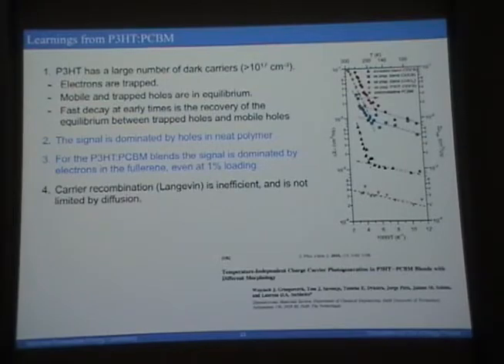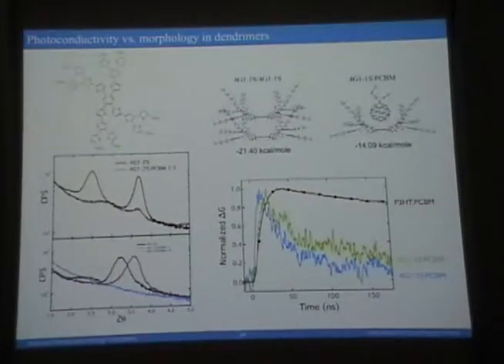This is a conclusion slide, which I'm going to jump over. There's a number of conclusions there. Here is some work we did with dendrimers, and this is Nikos's work. And what we discovered is that everything looks good with the dendrimer. They have the same repeat units, they absorb roughly in the same place, everything's going to be wonderful, and their devices don't work. And when you look at the microwave conductivity signal, it disappears very, very quickly.